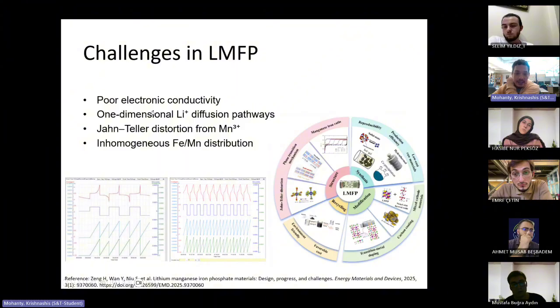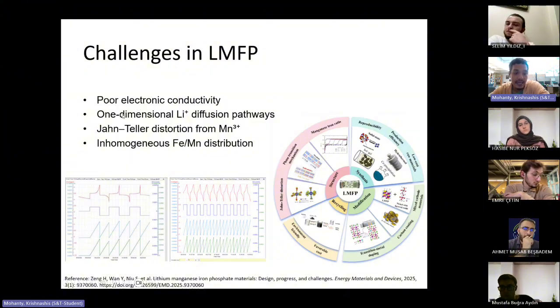And there could be many other reasons as well, such as the particle size itself, or the structure degrading because of Jahn-Teller distortion. There could be several factors which affect LMFP's electronic conductivity. But again, this is the foremost reason why we do not see LMFP being used extensively in the industry right now. This is a very big concern. Second, there are not enough pathways for lithium-ion diffusion because of the crystal structure itself. The pathways are so limited; the ions do not have free space to move about in the structure. And then we have Jahn-Teller distortion.